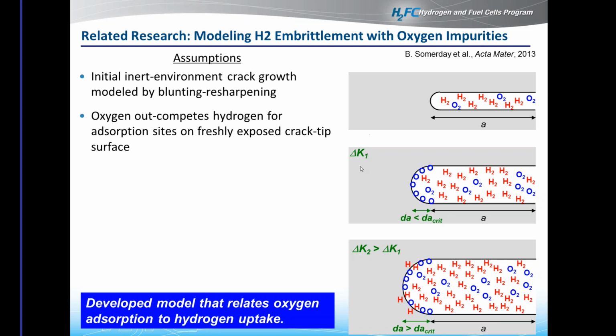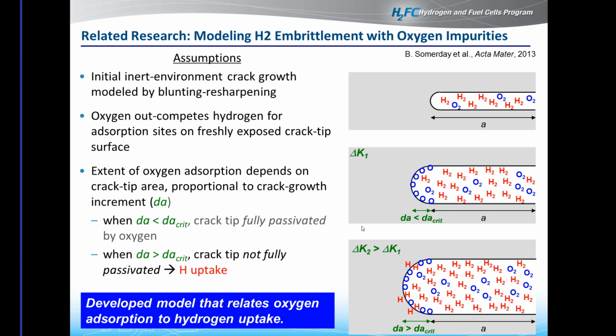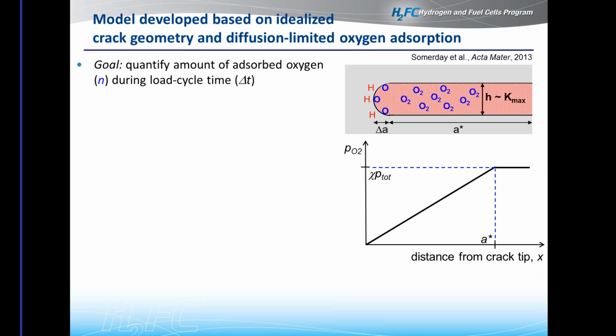So if we look at the lower delta K region, or if you look at a lower stress, at a specific delta K, you get a specific amount of crack growth that will occur. As the crack advances, this fresh surface is exposed, and in this situation, there's a sufficient amount of oxygen to fully passivate the surface, and therefore we don't see the effect of hydrogen-accelerated fatigue crack growth. Now, if we move to a higher delta K or a higher stress region, we're able to advance the crack even further. What this does is expose even more crack surface area that is fresh and essentially untainted. And essentially, in this case, there is not a sufficient amount of oxygen to fully passivate the surface. So this allows some hydrogen to get in, and this would be a scenario in which we begin to see hydrogen-accelerated fatigue crack growth because the oxygen is not able to fully passivate. So it really is just a competition between oxygen and hydrogen for surface sites.